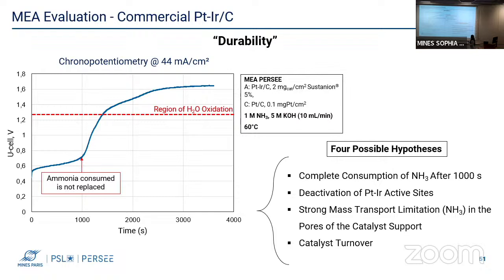Either the complete consumption of ammonia after 1000 seconds, the complete deactivation of the platinum-iridium active sites after this time, strong mass transport limitations in the support pores, or a matter of catalyst turnover, which is the number of moles of reactants that could be transformed into products by 1 mole of the catalyst. After calculating the mole percent of ammonia consumed during 1000 seconds to be 0.1 mole percent, it was possible for us to eliminate the first hypothesis.